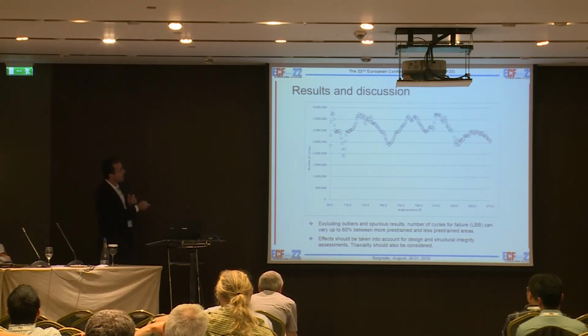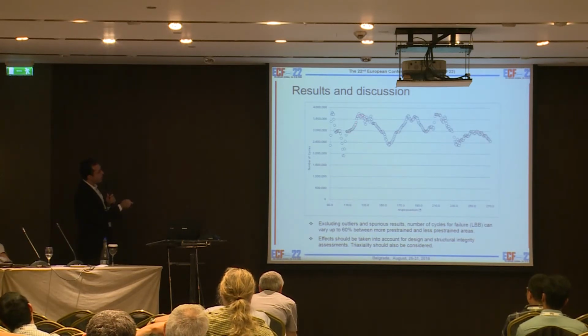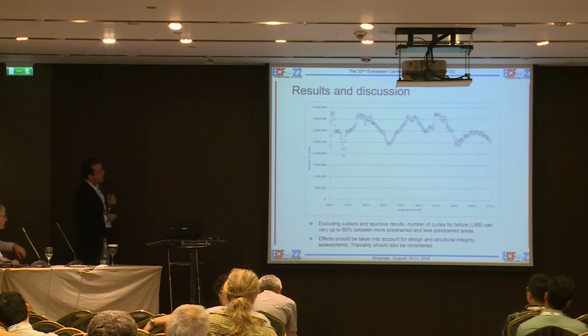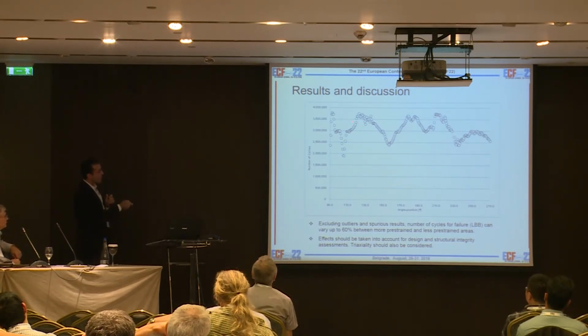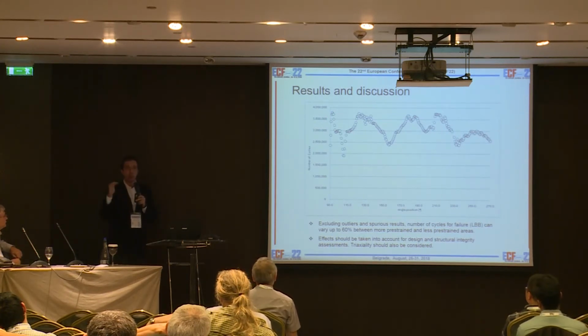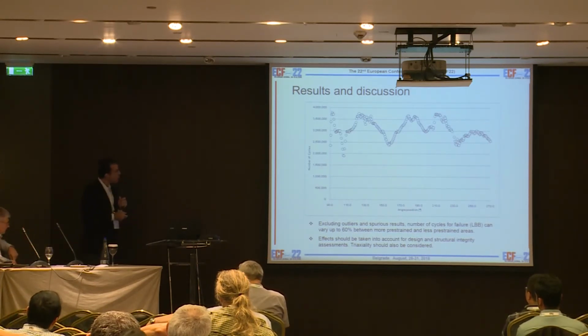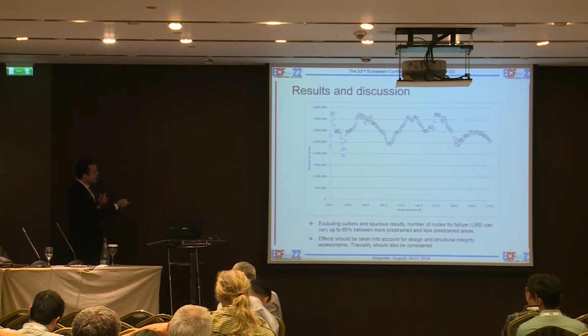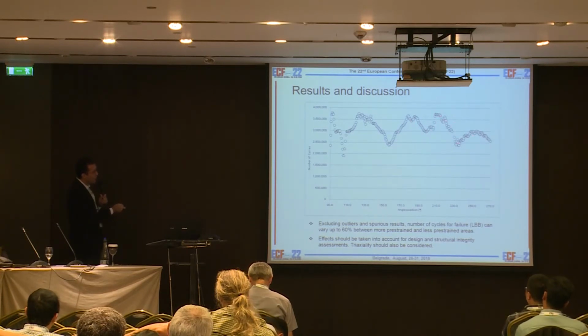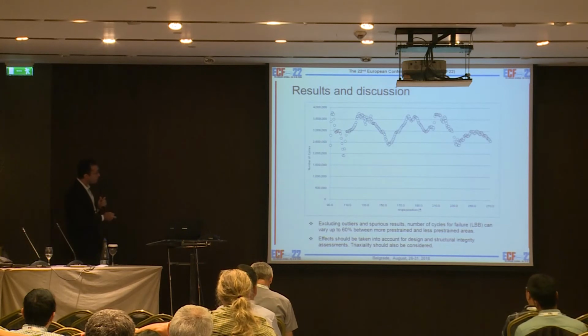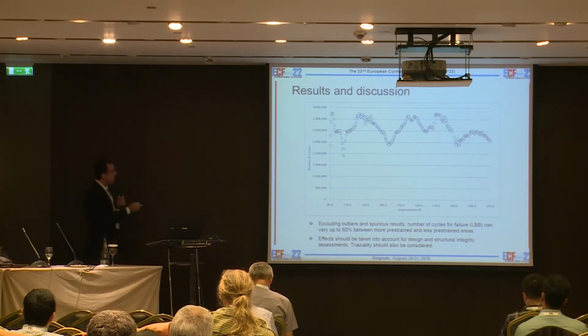And you can see that in some regions we have a larger number of cycles, and in some regions a smaller number of cycles. We should neglect this part because this is the initial contact between the tooling and the model, so it was not so smooth in terms of prestrain distribution. But here we can take into account this behavior, and it's very similar to the other models we developed that were a little bit more refined. So, excluding outliers and these spurious results, the difference between this number of cycles for failure and this number of cycles for failure in terms of LBB is around 60% if we take into account this region.